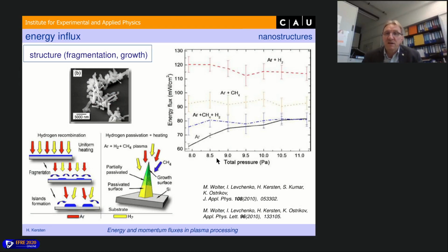As you can see here, just by changing the gas, here is the pure argon plasma, and here is the argon and hydrogen plasma. At the same conditions, the same power and the same pressure, we have here almost a double energy influx. And that means we heat up the surface for this structuring of the nickel layer. And why is this the case? This is due to the hydrogen.